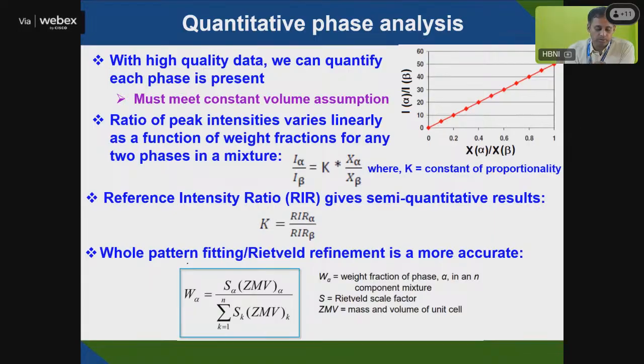It must be identified that the ratio of the peak intensities varies linearly with the weight fraction of the two components. If I have the intensity of the alpha component and the beta component, they will vary with the weight fraction of alpha and beta.